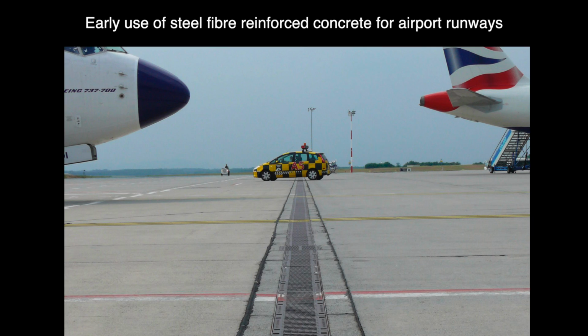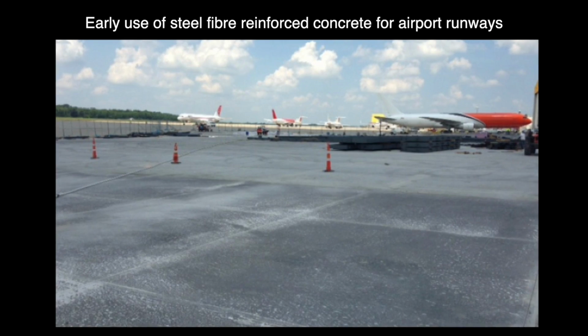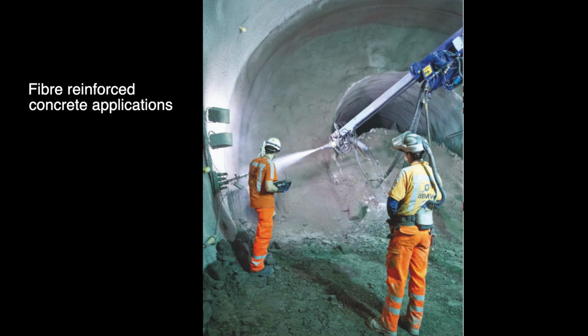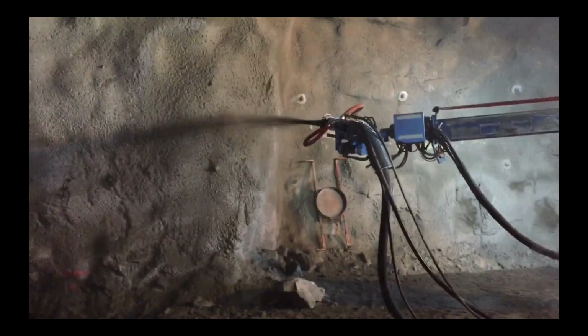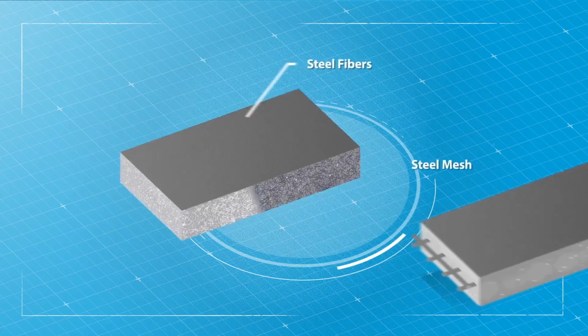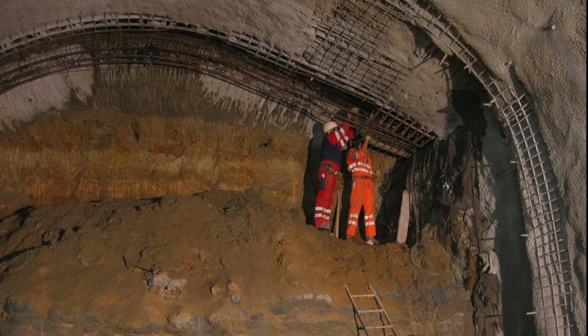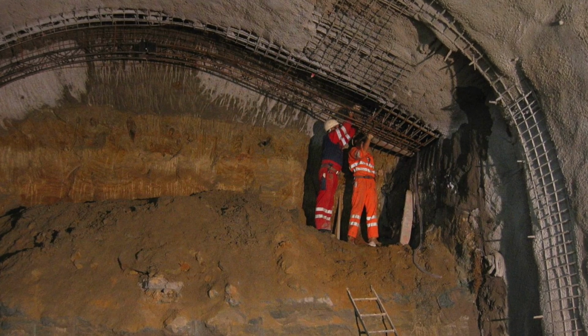From this basis, more and more applications showed up for airport pavement, where they were able to reduce the thickness almost by 50% by reinforcing the concrete with fibers. So we had shotcrete for tunnels, but using fibers, you can follow exactly the cross-section and you can stabilize immediately, because if you have to put a mesh into place, then you are losing quite some time. You need almost three times the time for installing the wire mesh than for shotcreting the same surface. And the advantage is that you're not losing that time, so the rock hasn't time to decompress, but you can stabilize it immediately.